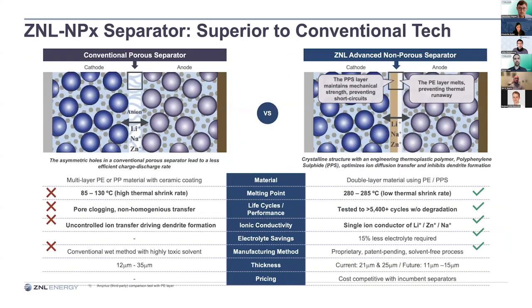So what's the difference between the conventional separator and ours? The conventional separators are porous, meaning they transport the ions through microporous structures and electrolytes. Ours is a PPS, it's non-porous, meaning it transports the ions through something called diffusion. There's a crystalline structure inside the PPS where the ions transport, and only the ions that you want to transport, be it lithium ions, sodium ions, or zinc ions.